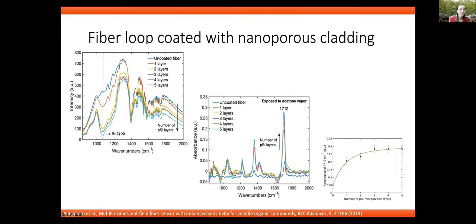And what happens is that our porous silicon, while we went through all this process of coating it and breaking it to small particles, oxidized because silicon will spontaneously oxidize in air to form silica. So we can see here very strong silica bonds. So effectively we are coating nanoporous silica particles on top of the fiber.